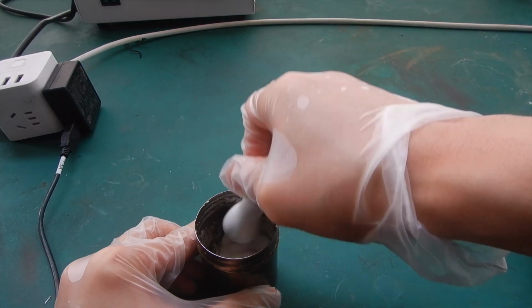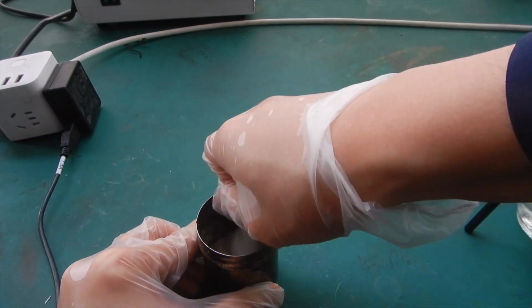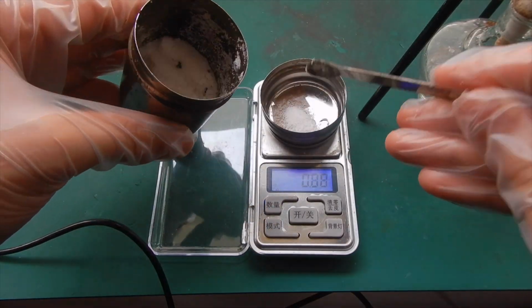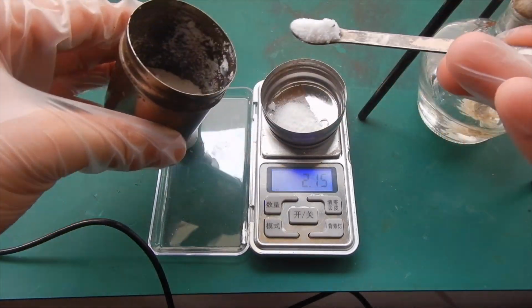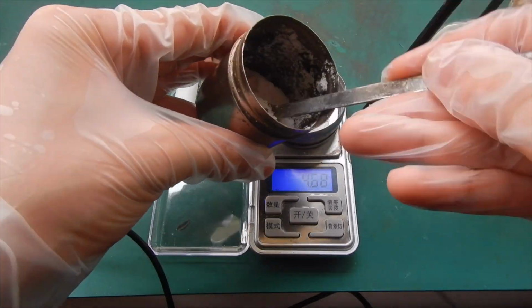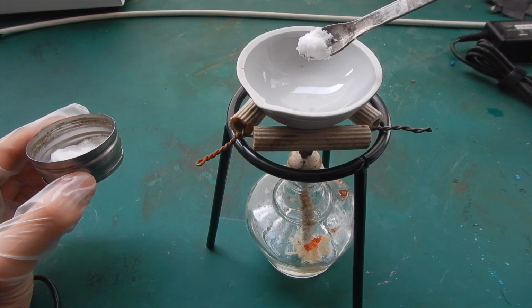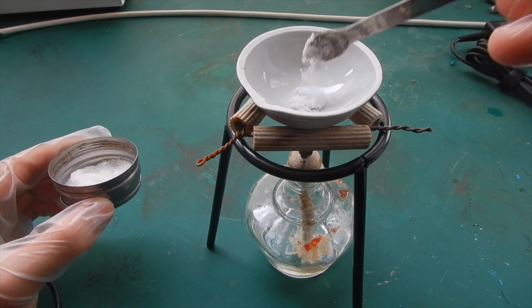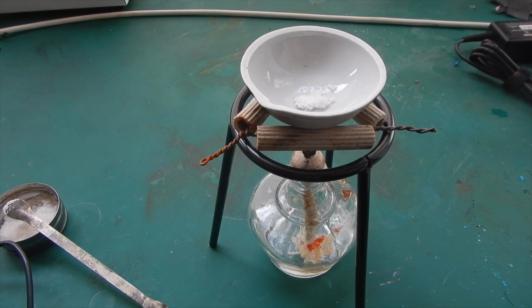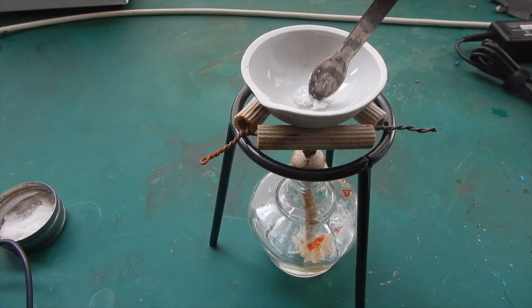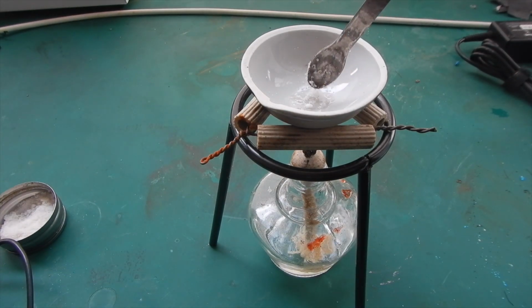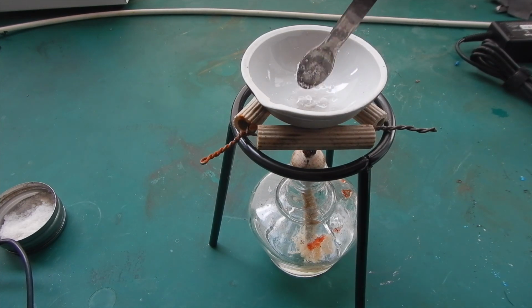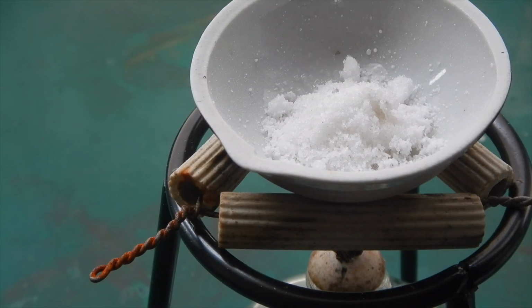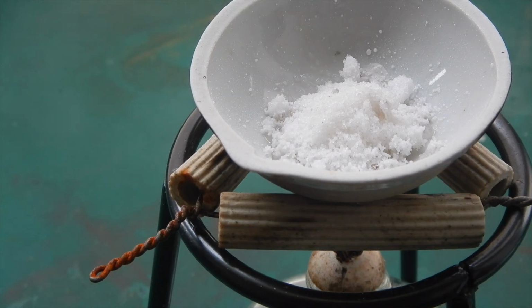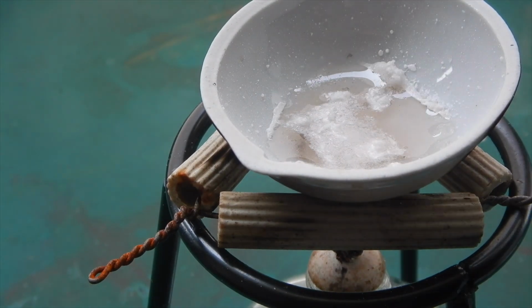There were a few large chunks of salt in it, so I crushed them up with a mortar. I then measured out about 10 grams of the mixture in a container. The exact amount isn't critical. I carefully sprinkled some salt mixture in the center of the dish. It first sizzled and let off a bunch of water vapor, and then quickly melted into a clear liquid. I kept adding the salt and stirring the molten mixture until the initial 10 grams were all added. The molten mixture was not very viscous, and it looked just like normal water.